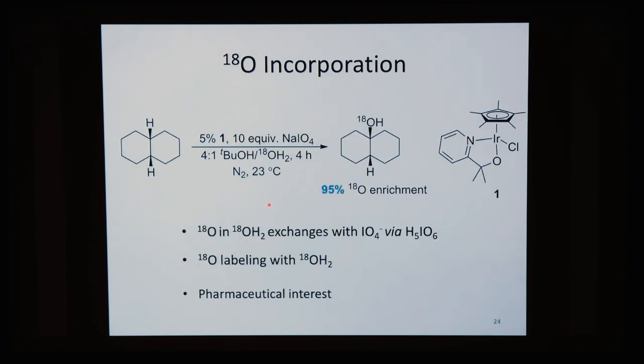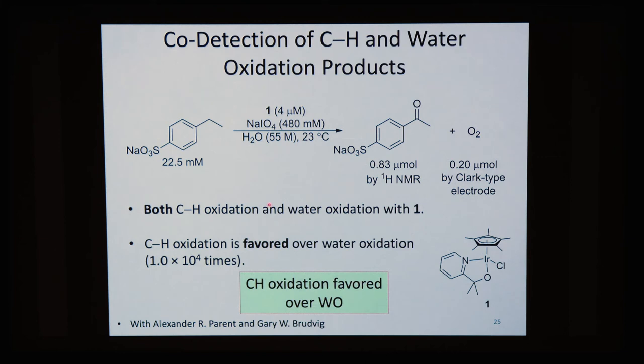And O18 incorporation is possible very easily with 95% O18 enrichment. And this apparently is of pharmaceutical interest, that they often use isotopes to look at their products. We also ran a CH and water oxidation simultaneously, with a big excess of water and a small amount of a water-soluble CH substrate. And we found that in this case, the CH oxidation was favored over water oxidation by 10 to the 4. So it's much easier to oxidize a CH bond than it is to oxidize water. And indeed, the Cp* is not burnt off in the CH experiments. So the oxygen is able to attack the substrate rather than the Cp* of a neighboring iridium.